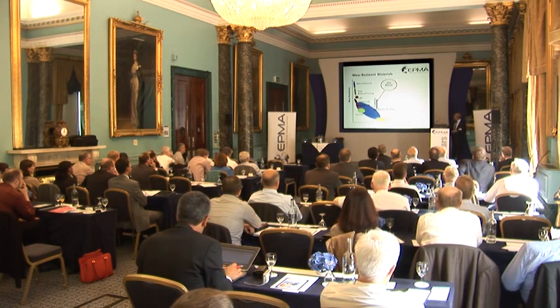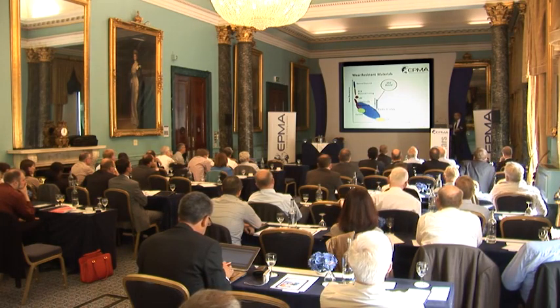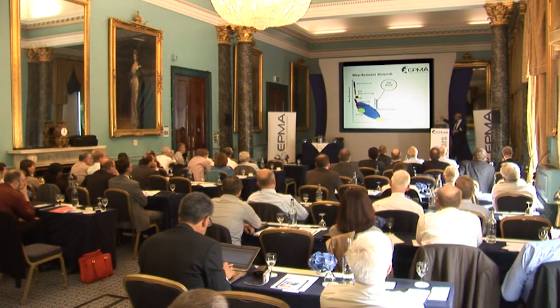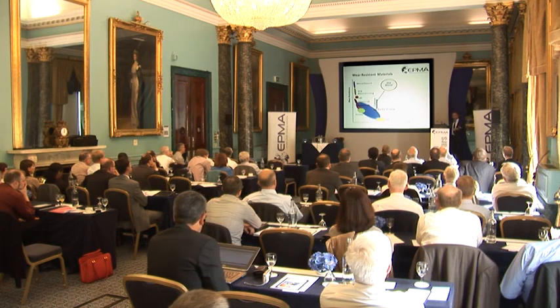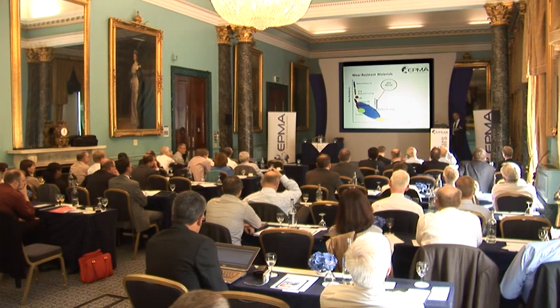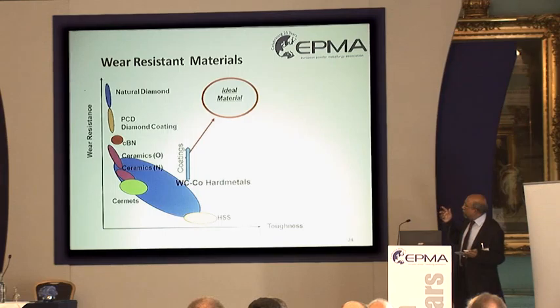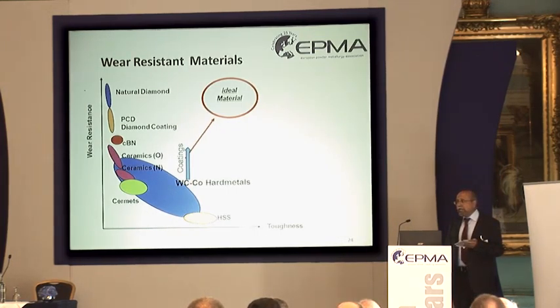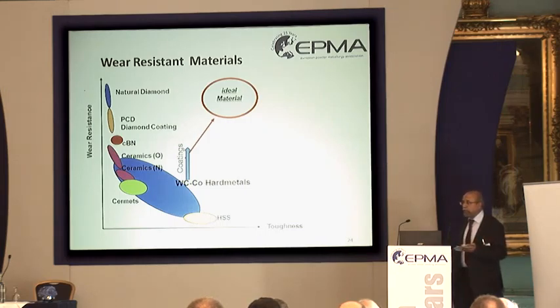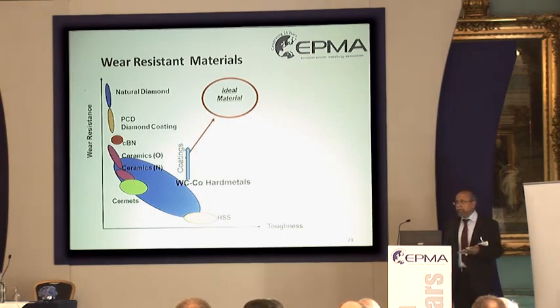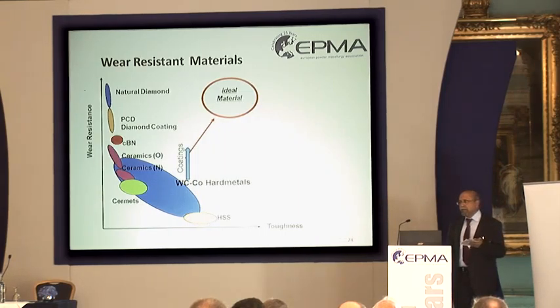So this diagram shows you that coatings have gone a long way to improve your wear resistance, and even ceramics or cermets are coated with hard materials nowadays to improve their lifetime by a factor of 100%. And 25 years ago, we knew about diamond coatings, but the adhesion was very poor. Nowadays, we make millions of 3/8 inch drills for aircraft. Every Airbus 380 has 50,000 holes which have been drilled just for rivets. I don't talk about the doors and the windows and whatever, but just the rivets. And it's all CFC and titanium, and only using diamond-coated tungsten carbide can we reach the requirements of this industry.